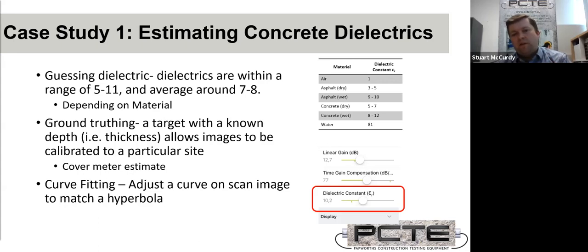Here's some measurements for dielectric. You can see concrete ranges from about 5 to 12. Water has a dielectric of 81, which is quite high. So the more water in the concrete, the higher the concrete's dielectric. We can just guess and say it's about 7 as an average for concrete. If we do that, we get a depth measurement and it's an estimate. We could do ground truthing. So we could go to an area where we actually knew what the thickness was, if we did a core, or we could measure somewhere on the slab to get its actual thickness. And we could use that value to correct our dielectric to be more accurate.